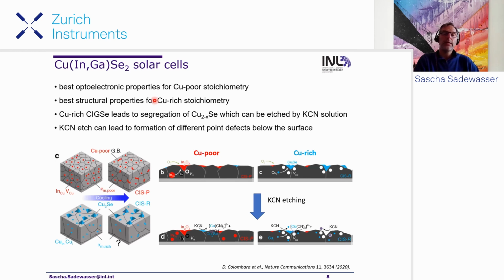And actually in the growth process that gives you the best efficiency, the best performance, you start with a copper poor, then you go through a copper rich phase, and then you finish the growth with a copper poor deposition. So you go through these regimes of copper poor and copper rich during your growth process to optimize both the optoelectronic and the structural properties. If you end up with a copper rich copper indium gallium diselenide, then you will actually get copper selenide secondary phases that normally happen on the surface here. And that can be etched away easily with a KCN etching. So this KCN etching attacks favorably the copper selenide materials.